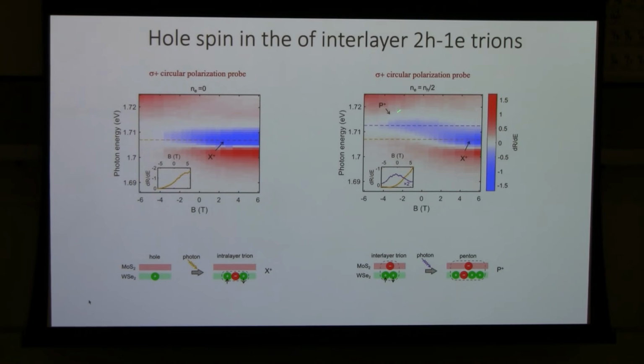So let's focus on the top dashed line first. What you can see is this feature is largely symmetric between positive field and negative field. That means the state is not polarized by the magnetic field. It's an indication that the holes in this system are in more of a spin singlet configuration, which corresponds to a bound trion. Because if you have a bound trion, the electron is bound with two positive charges, and to lower its energy, the two holes have to have opposite spins. Since they have net zero spin, when you apply a magnetic field, you cannot polarize them. So the behavior is symmetric.